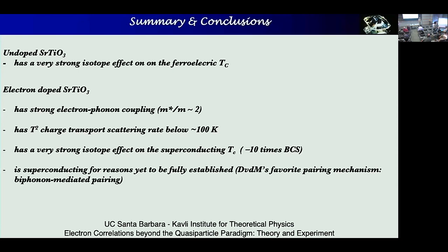Peter? Hi, Dirk here. So I had a question about M star. There are quite a few papers, if you go back 30 years, saying the plasma frequency in this material is temperature dependent. So it changes, I think, a factor of 3 or 4 between room temperature and, say, 20 Kelvin. Sometimes people attribute that to changing M star. The alternative is you have to attribute it to something else changing, like the density. I was just wondering if you had any idea what it could be, and does your M star determined in this way give you a number that changes with temperature? Yeah, it changes with temperature. By factors of 3 or 6? No, a factor of 2 if you go to room temperature. Actually, it's getting smaller if you go to room temperature. It goes down.